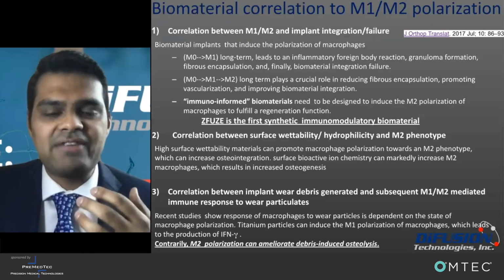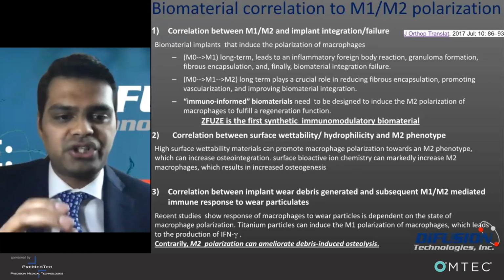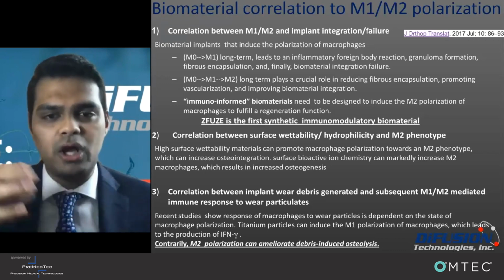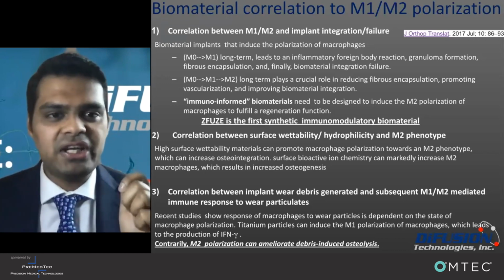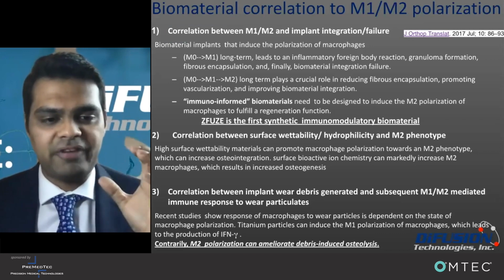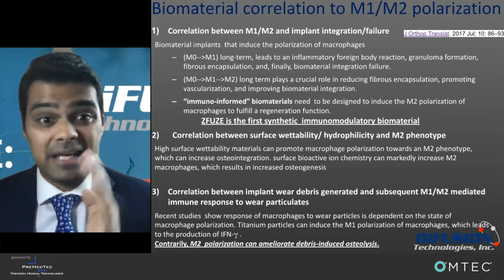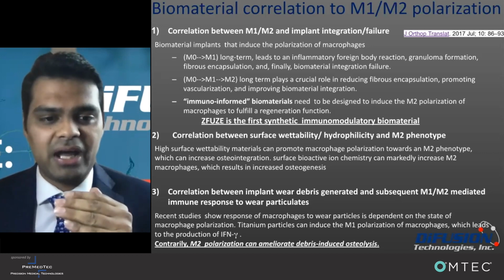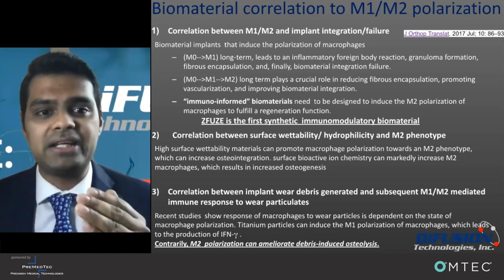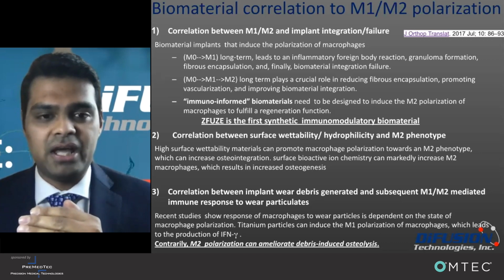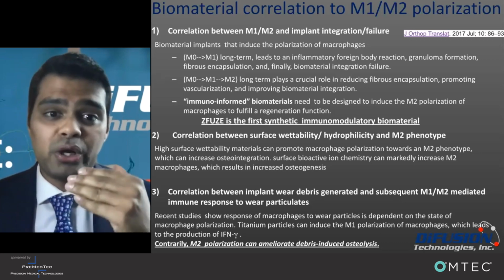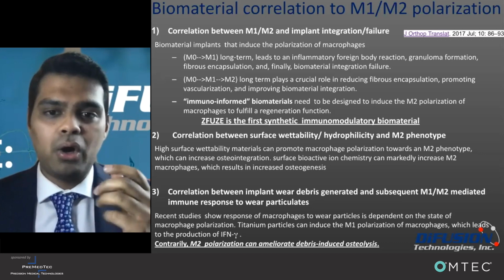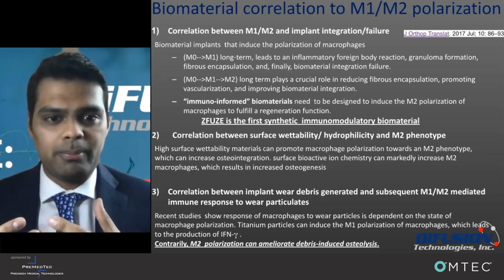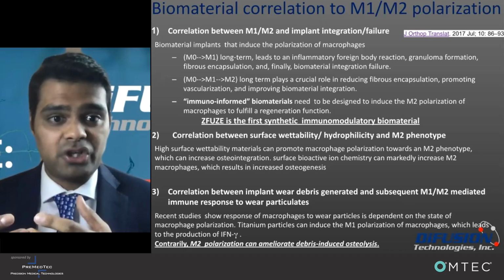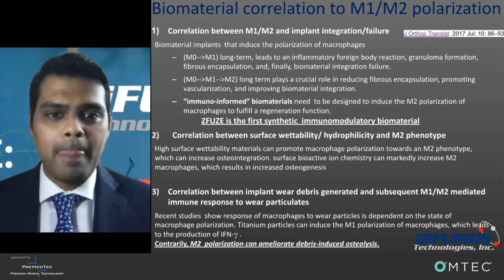And this basically drives home the correlation between osteoimmunology and bone response, that initially from an M0 resting macrophage phenotype, an M1 phenotype is necessary because it brings the other actors to the site of injury. But then quickly it needs to shuttle into an M2 pro-reparative state. So we need to develop immuno-informed biomaterials that help induce this M2 polarization of macrophages, since it has a regenerative function. And Z-Fuse, to our knowledge, is the first synthetic immunomodulatory biomaterial that does this.